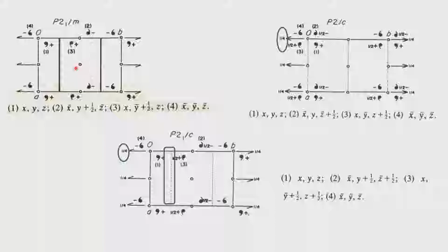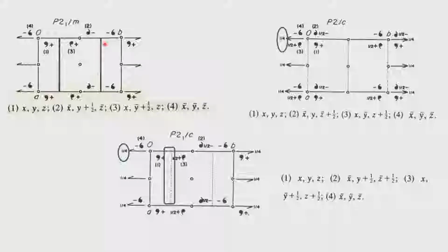And the mirror symmetry is now moved away from the origin, the intersection of the origin and the 2-1 screw axis, by 1/4. So, the mirror now appears at 1/4 and 3/4, and therefore, the symmetry operations now become slightly different. So, if you take the point number 1, operate now the presence of the 2-1 screw axis.